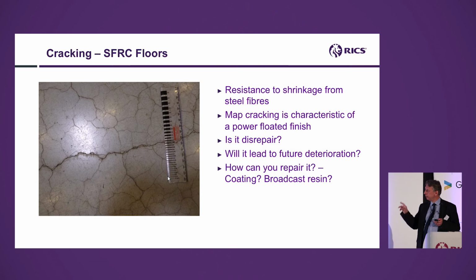And we were concerned that over a period of time, you would get more wear. The little individual lenses would pop off and you get deterioration and so on and so forth. In the end, the landlord agreed to broadcast a very thin resin over the whole floor to help seal those cracks and prevent deterioration. I've no idea what the law of dilapidations is in Belgium, but this was an interesting case. Is cracking like that disrepair? Possibly not. Perhaps it could reach a certain level where you do need to do something about it. Perhaps that is good enough to trigger an obligation.